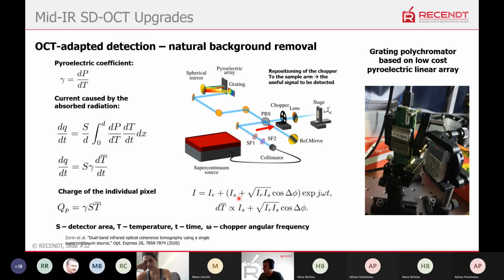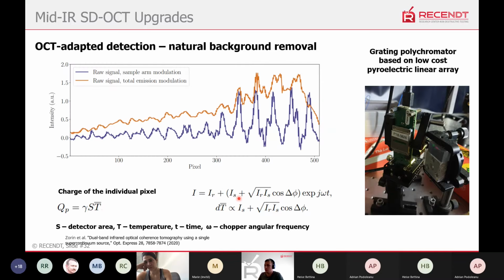And actually it was quite an advantage in a lot of cases. For example, I could go to longer integration times, and it would not saturate my detector. Saturation is not maybe the right word for pyroelectrics, but there is still some floor. And it's just a comparison for this standard configuration I had and the configuration I would get if I put the chopper in the sample arm. So it's a very simple procedure which allowed to extend dynamic range and got a little bit better sensitivity.